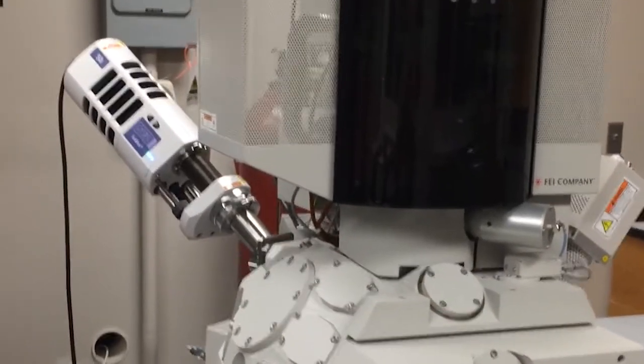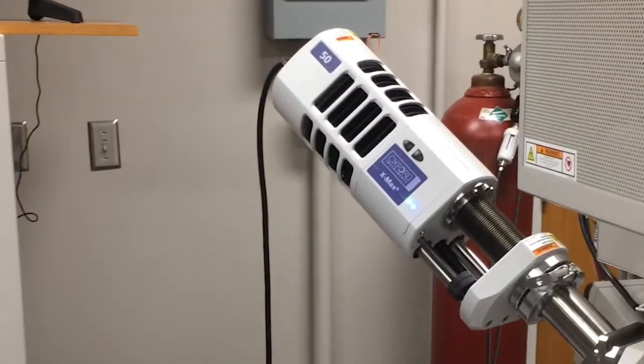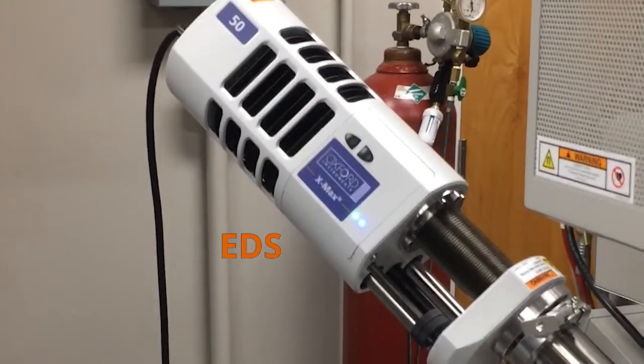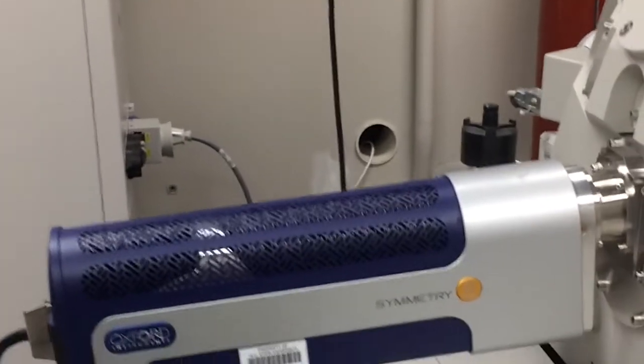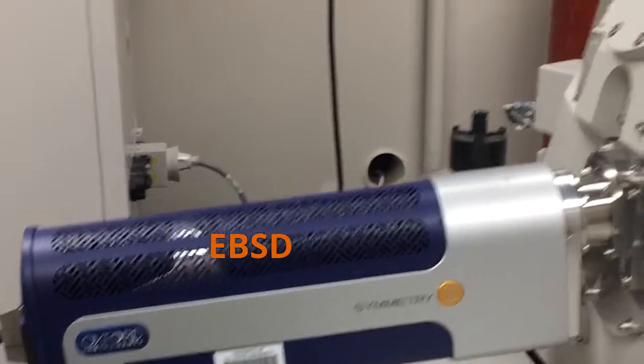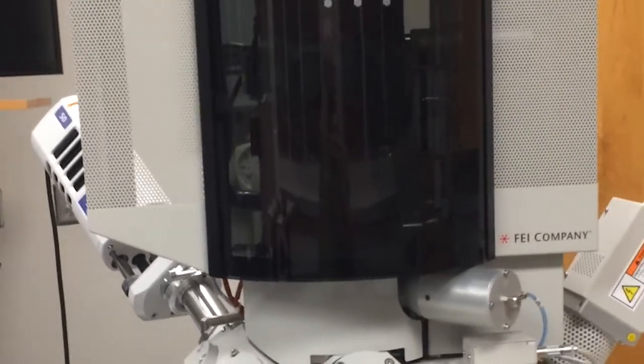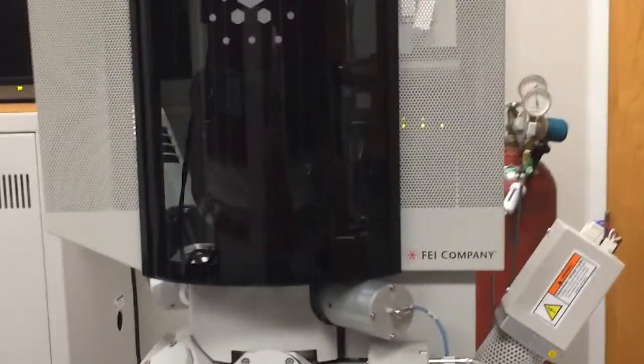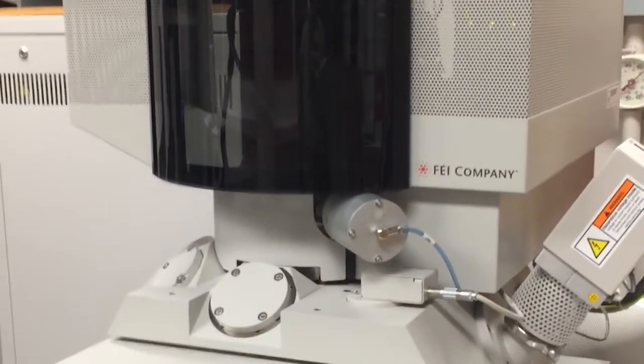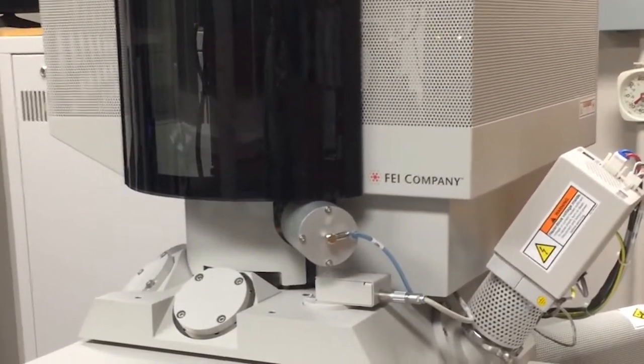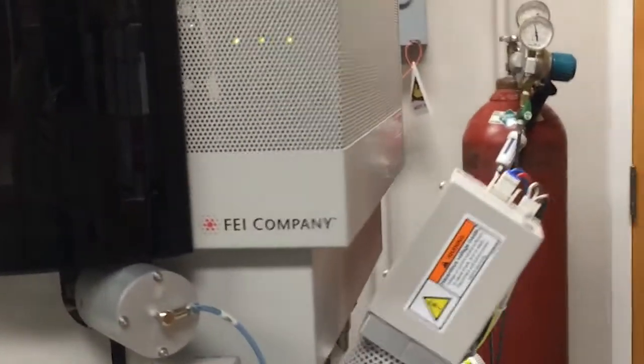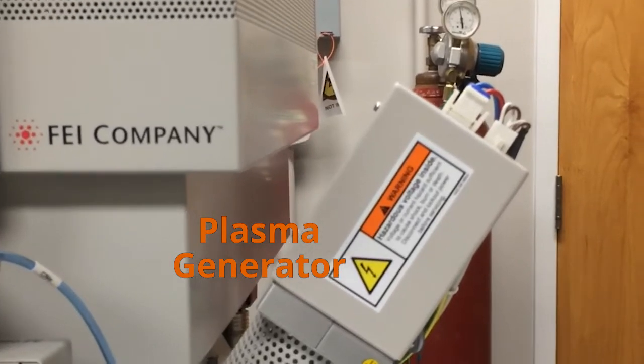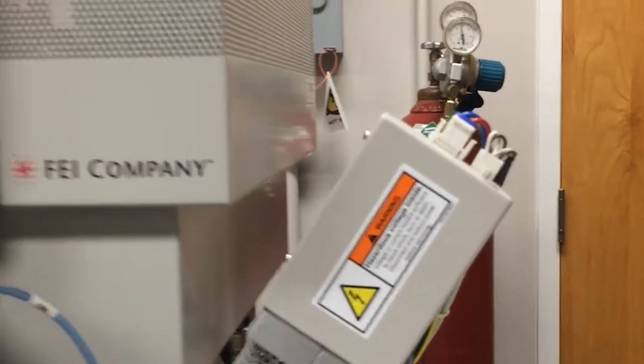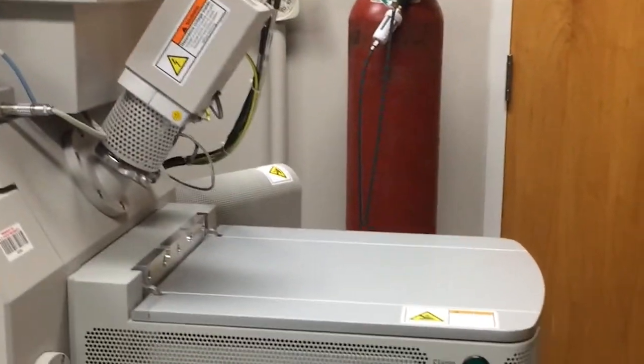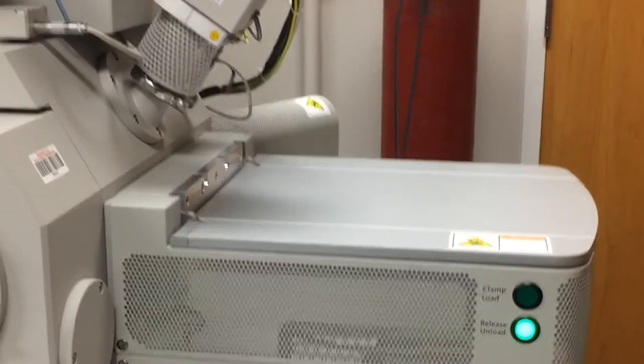The Verios SEM is equipped with an energy dispersive X-ray spectrometer detector, an electron backscatter diffraction detector. It also has a standard complement of an Everhart-Thornley secondary electron detector, a through the lens secondary electron detector for ultra-high resolution mode. There is a standard insertable backscatter detector for compositional contrast. The item right here on the side of the column is an oxygen plasma generator for cleaning samples in situ, and the system is also equipped with a load lock so the inside of the microscope stays under vacuum and clean.